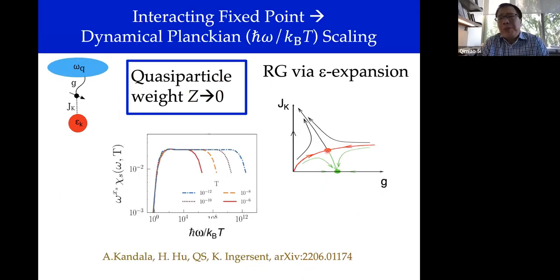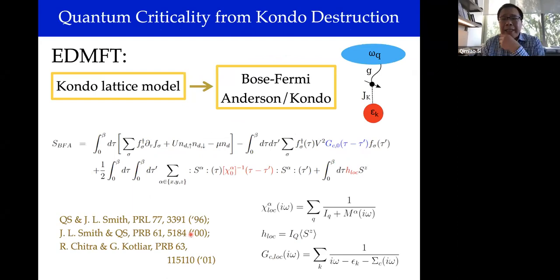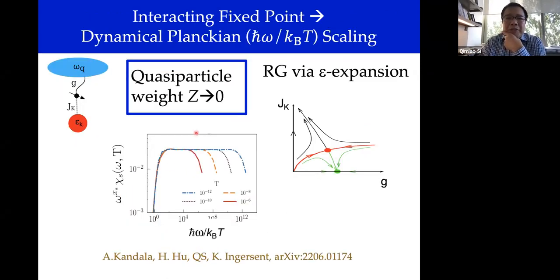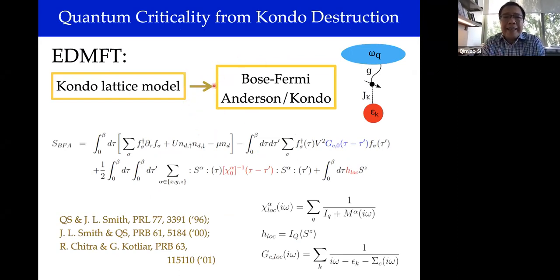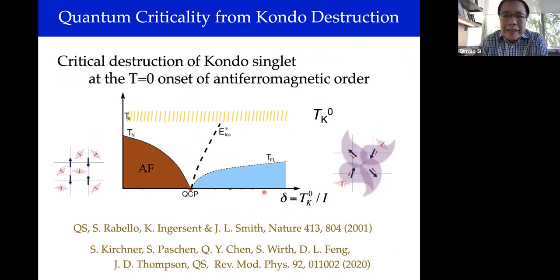And also this is a critical point where all the energy scales become a scale-invariant spectrum. As a result, k_B T is the only scale in the problem, and one can probe a number of different physical quantities as a function of frequency and temperature to see that it has the scaling ħω/k_B T, with the Planck constant in it. So that's a characterization of this Bose-Fermi Kondo model per se, and with this understanding we can proceed to analyze the whole lattice model, whose equations I've written down here, which I think I'll skip describing unless there's a question.